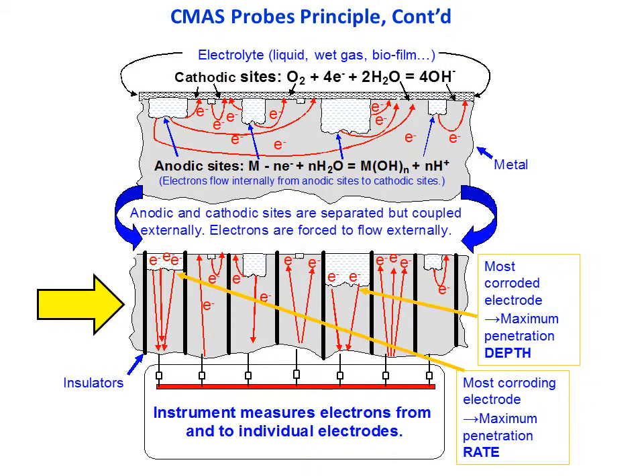CMAS technology is implemented by cutting the metal into small electrodes approximately 1 mm in surface diameter and insulating each electrode with an epoxy or ceramic insulation. Each electrode is coupled to a common joint through a ZRA, zero resistance ammeter, so that the current flow through each electrode can be measured and quantified. Due to the small surface area of the electrodes, the corroded electrodes simulate the behavior of a single pit, and the current from the most corroding electrode can be used to calculate the maximum penetration rate, and charge from the most corroded electrode can be used to calculate the maximum penetration depth.